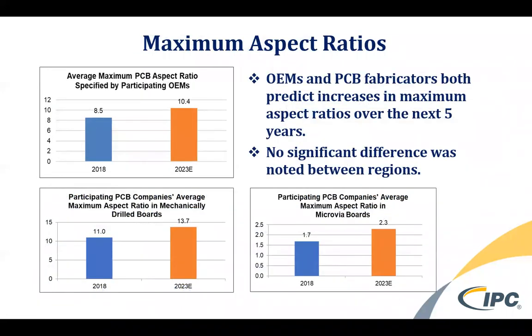In addition, now we're seeing the aspect ratios increase, the thickness of the board divided by the diameter of the hole. That is also causing us to have changes in how we not only drill mechanically, but also how we process plating. Many of us, as we move up the curve in terms of getting better throwing power and getting better uniform distribution throughout the via and on the surface, this requires us to look at potentially periodic pulse reverse plating in place of direct current plating to improve the distribution and the throwing power in these higher aspect ratio boards.